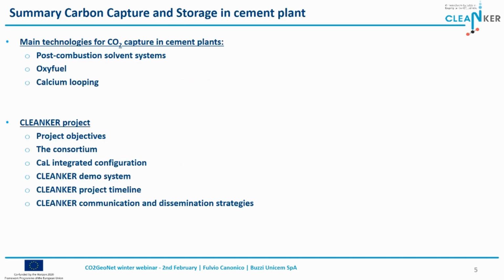And so what can we do in our cement plant? You know that a cement plant is a very complex industry. It's really a heavy industry. We are dealing with quite a lot of material. A plant may produce more than 1 million tons of cement, but of course you need to play with millions of tons of raw material and of fuel. So this is not really an easy thing to do, to really change our process quite a lot, also because the CO2 is a relevant part of the emissions we have. You have to think that for every ton of clinker we are emitting more or less 1 ton of CO2.